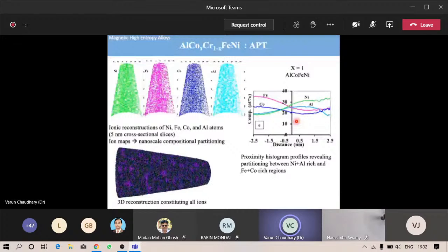Here are the atom probe tomography results for the x equal to 1 composition, to see at the atomic scale what is happening, whether there is any partitioning or not. Using EDX and similar techniques, it looked very homogeneous, but at the nanoscale there is some partitioning: on one side we have more iron and cobalt, and on the other side we have nickel and aluminum. We are trying to use this to understand how we can make a material with low coercivity and high strength by doing some Lorentz microscopy studies. This work is ongoing.